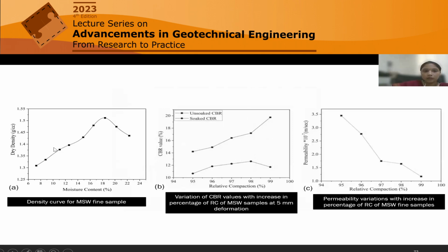This one we are using for possible field application. This first one is the compaction curve. Here you can see MDD and OMC, and the middle one is the CBR results. If you see, the unsoaked CBR is quite high compared to the soaked one. The soaked one we repeated 2-3 times, but we got this result only. The unsoaked CBR we are getting is more than 14%, but for the soaked one, even for 95 it is more than 10, which is above the requirement as per our IRC guideline. For subgrade it should be more than 10, and for embankment fill 5% minimum, this CBR value.